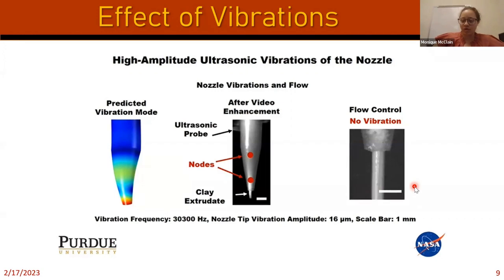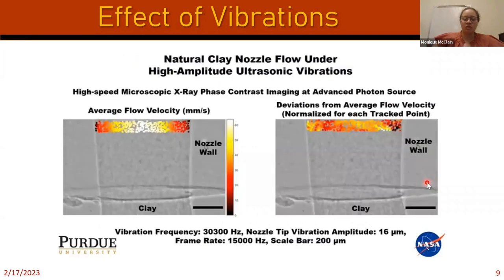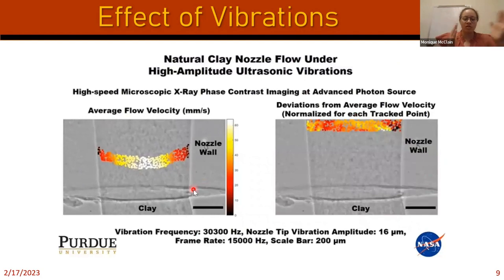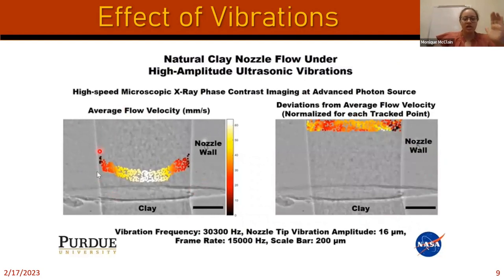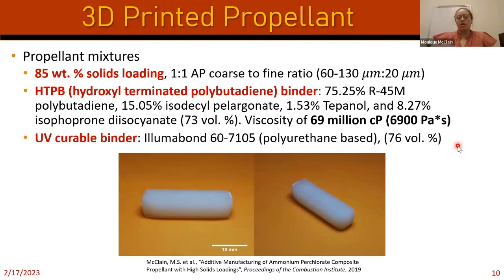I'm going to start playing it now. You can see it's barely coming out without vibrations, but it's way faster with the vibrations. The reason for that is, looking at the nozzle walls and the material flowing out, we're shaking the nozzle in a way that this material slides out without experiencing the same amount of friction that it normally would without the vibrations. So as you can see, it allowed us to print these viscous mixtures orders of magnitude faster at this very small nozzle diameter. I think these were 600 micron nozzles, and I think the actual diameter was about 400 micron. That was the basis of this 3D printing technique.